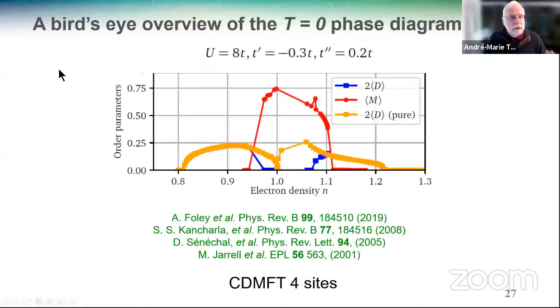So let's start with a bird's eye view overview of the zero temperature phase diagram that you get with this method. This is for U equals 8, and these are typical parameters for the cuprates. Here is the order parameter as a function of electron density, the electron-doped case and the hole-doped case. Without antiferromagnetism, you get d-wave superconductivity like this. And if you include antiferromagnetism, then you get this asymmetry of the phase diagram, and it ends at sort of 95%. Because of the competition, superconductivity dies here.